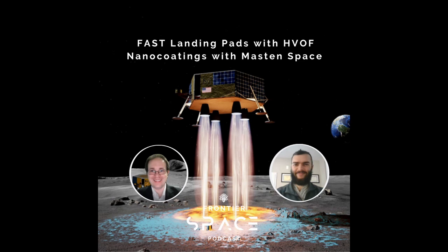One of the reasons we did that, and it was a very intentional choice, is because mass is so expensive when you go to the moon. So you really want to create the thinnest pad possible to stop the ejecta problem and then hone in on your optimal solution. It's not only the mass of the material you're bringing to build the landing pad, it's also the mass of the propellant you need to deploy this while hovering. It takes about 12 to 15 seconds to deploy this on your final descent from 30 to 50 meters altitude. So the spacecraft has to null its descent velocity and then hover there for a few seconds, which is a huge propellant sink, and that all costs money and launch mass.